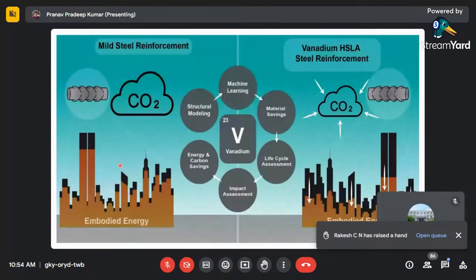So with this idea, this slide shows an overview of how the 4 different phases of the life cycle assessment framework that I presented at the beginning clearly show how the reduction in embodied energy and carbon could be obtained by microalloying vanadium into steel. And a similar approach may be adopted to efficiently conduct material flow analysis and determine the impact of other waste-derived materials in concrete as well. It's not just limited to vanadium or steel. This analysis could be extended and implemented into other different materials.